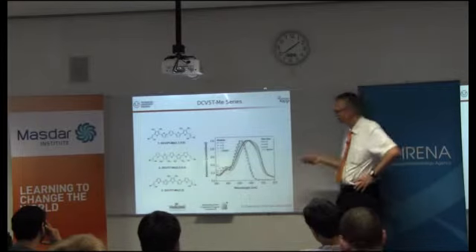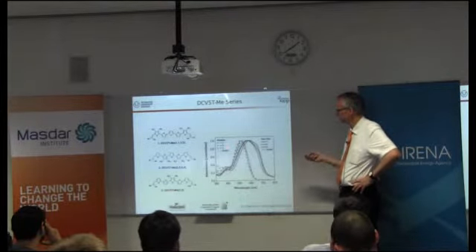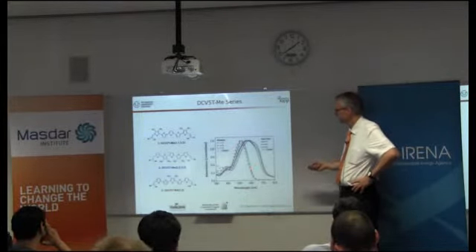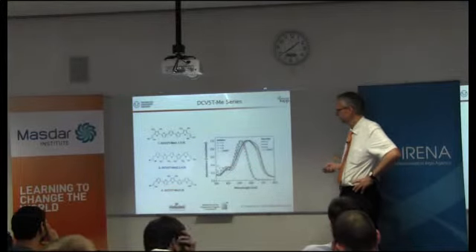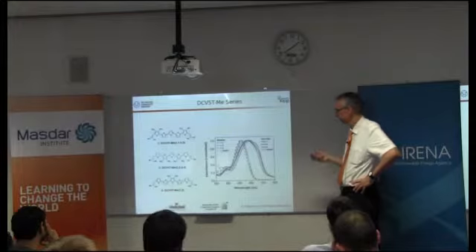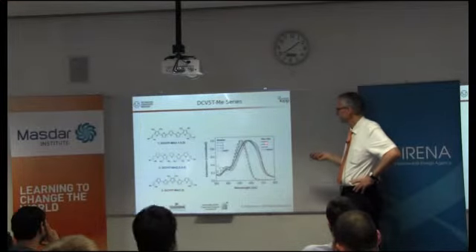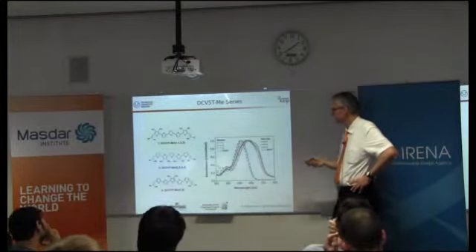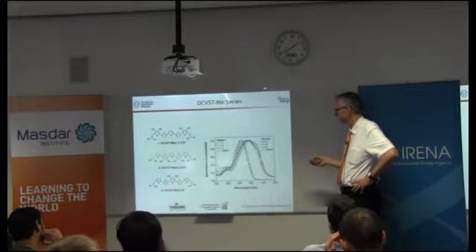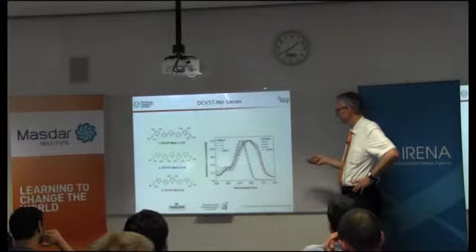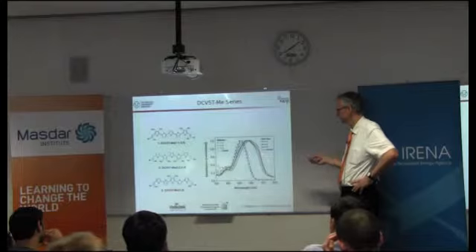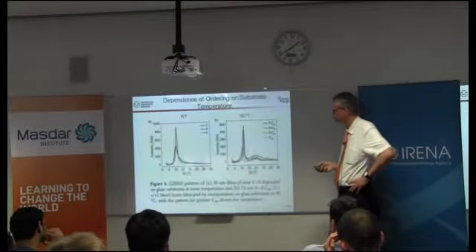If you do absorption spectroscopy of these molecules in solution, actually you see that they are almost identical. These are the dashed lines. They absorb in the visible strongly. They are very colorful substances. When you do the thin film here, you see a strong redshift, and you see that there are somewhat larger differences already between these molecules.